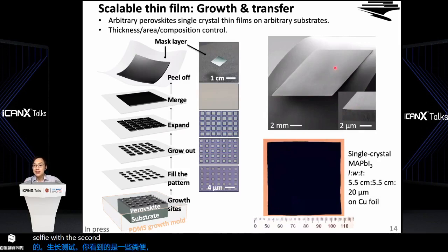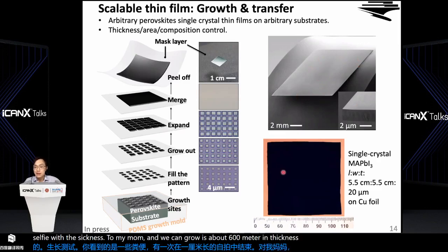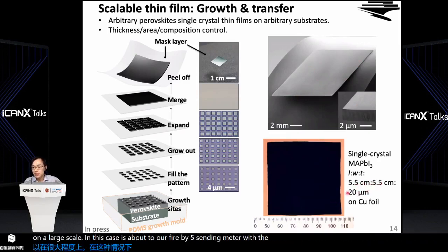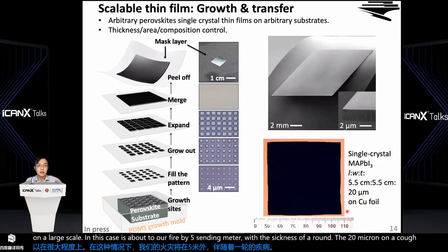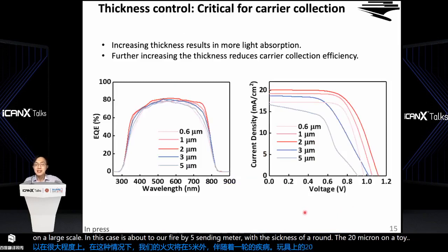thickness. And after the thin film is transferred onto a curved PDMS substrate, the thin film can be on a large scale. In this case, it's about 5 by 5 centimeter with a thickness of around 20 micron on a copper foil. So this can be scalable to even larger area if we have this large single crystal as the substrate. Why is thickness critical, right?